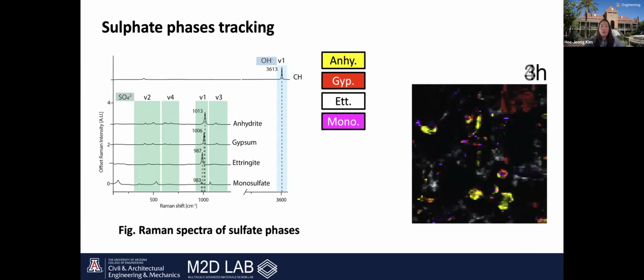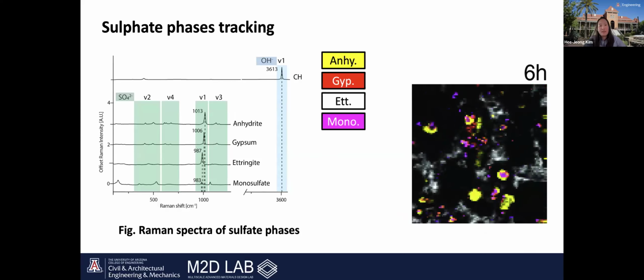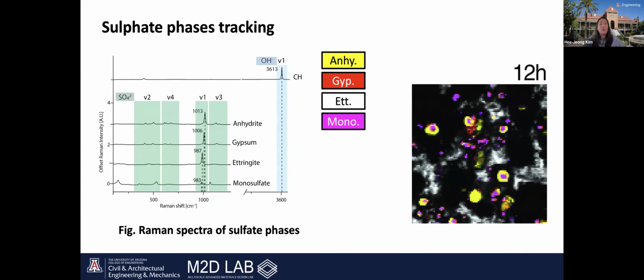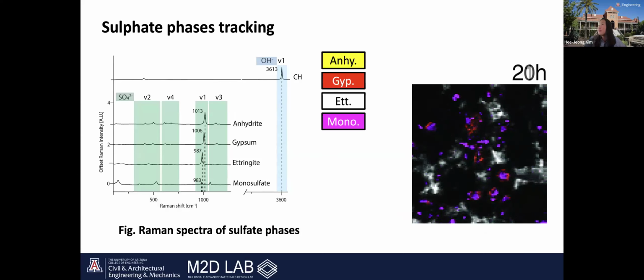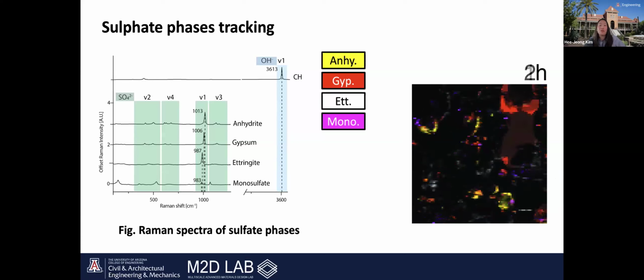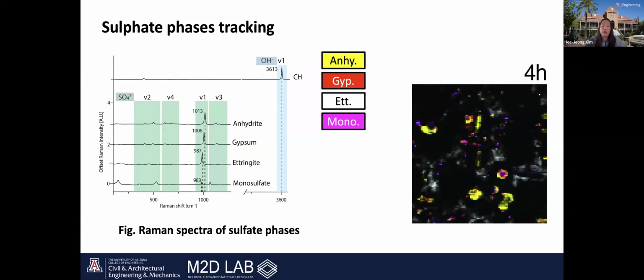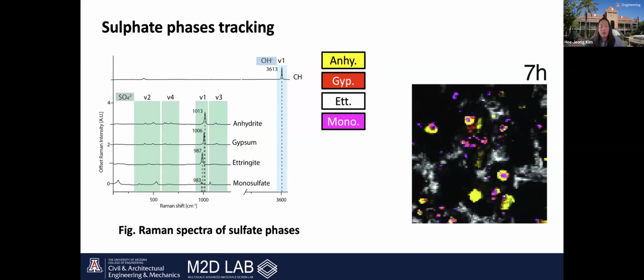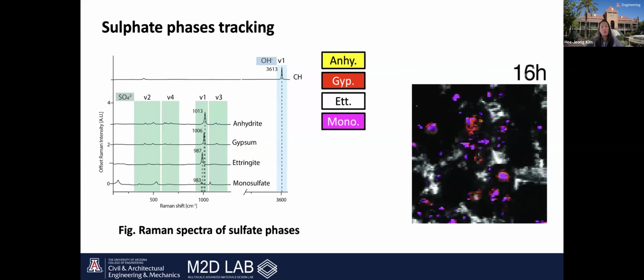Raman spectroscopy can be used not only to study OH phases, but also to differentiate the various surface phases in cement. The Raman mapping image shows that a large amount of ettringite is already formed within just an hour of hydration. It helps densify the cement matrix structure, contributing to the early strength development and stability of the material. And this Raman technique can be applied to various types of cement research, as demonstrated in the following studies.